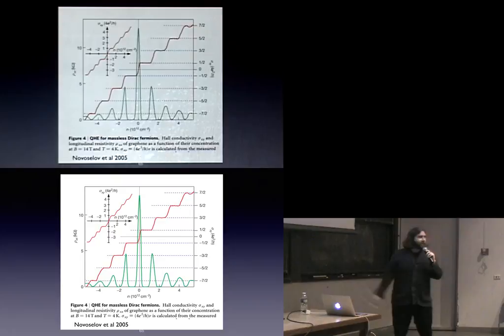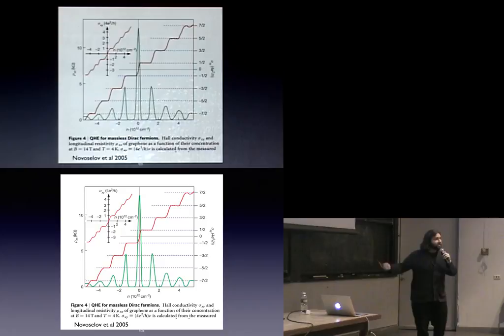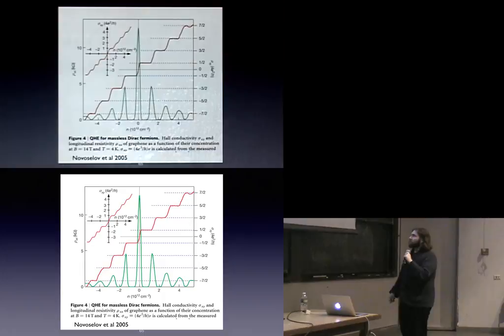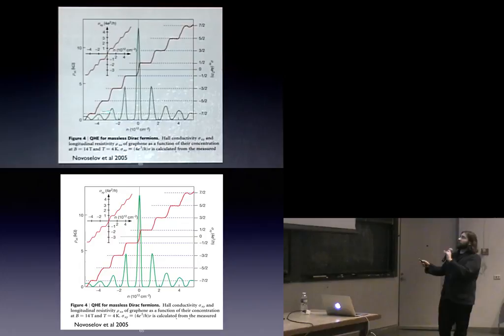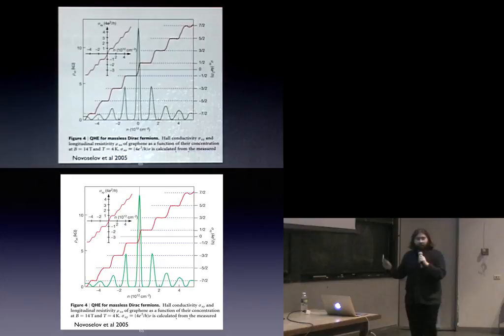The quantum Hall effect for a piece of graphene shows something very puzzling: there are plateaus, but they're not at nice integer values — they're at half-integer values: 1/2, 3/2, 5/2, 7/2, and so forth. And similarly going negative: −1/2, −3/2, −5/2, etc. This is from a Nature article from around 2005. Here you're starting to see precisely the pattern I wanted — a system where I have nice integer states whose Hall conductance is half-integer, and it can be positive or negative.